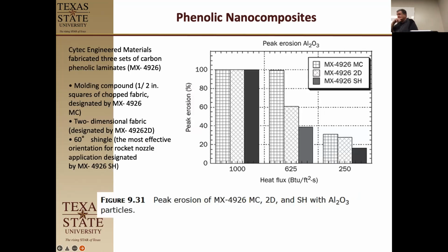Okay, so now they mix their stuff in, and so they have different things, and then they also added a little bit of aluminum oxide. So we're going to use a standard phenolic mat, and they're not going to use the standard mix of the phenolic resin that already comes on it, but they're going to change a couple of things by adding three different materials in the system and then look for their erosion rates. So if you look at the erosion rates based on heat flux right here, peak erosion percent. At 1,000 heat flux, they all completely disappeared. 100% failed. 100% erosion.